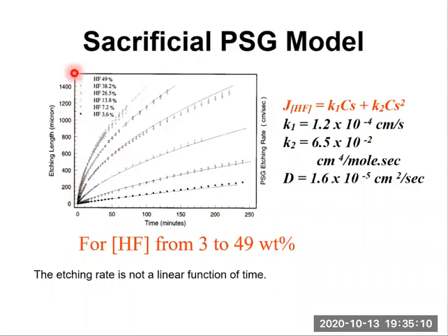This figure plots the measured etching length as a function of etching time for different HF concentrations, from 3 to 49%. We can observe that the higher the HF concentration, the faster the etching. This curve stands for 3.6%, and this one stands for 49%. So the higher the HF concentration, the faster the etching. This is kind of obvious. In addition, we can observe that the etching rate is not a linear function of time, but a non-linear function of time.